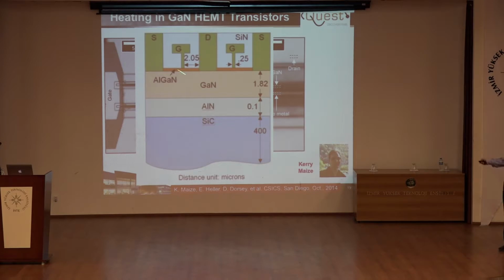Typically, heating increases the electron resistance, decreases the mobility, so the device becomes less efficient. That's one thing. The second is reliability. A lot of the devices have a finite lifetime, and the lifetime is exponentially related to temperature. Typically, 10 degrees excess in temperature reduces the lifetime by a factor of 2. So really, we need to consider the temperature at the location of the heat, and we need to minimize it.